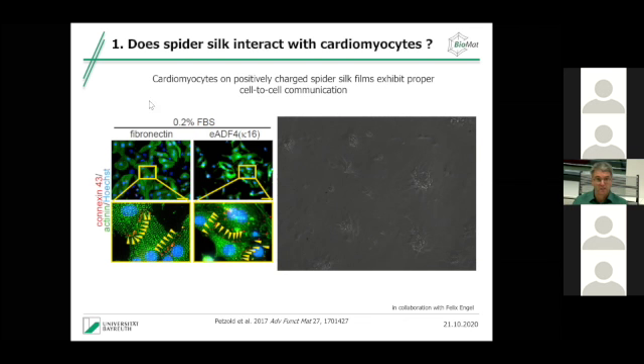And all of a sudden, so we call this protein eADF4, for engineered Araneus diadematus, so that's the spider, fibroin 4. This is the natural counterpart, kappa 16. Kappa stands for K for lysine, and we have 16 lysines in there. And if we make this engineered spider silk protein, you see that the cardiomyocytes now attach to the surface, they spread, they proliferate, they connect, and in the movie you see they even start to contract after 2 or 3 days.